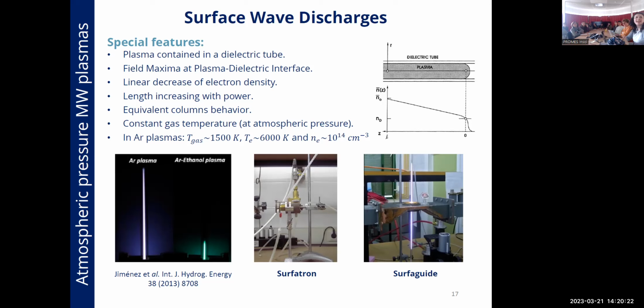Okay, what I was saying is that we are working with two kinds of microwave discharges. The first one, presented in this slide, is what we call surface wave discharges. These plasmas are created inside a quartz tube. Something very characteristic of this kind of plasma is that the electromagnetic field has its maximum at the walls, and it helps the propagation of the waves. Which are the characteristic plasma parameters of this kind of plasma? We are working with electron densities with these values, this energy for the electrons, and something very interesting is that all along the plasma column, we have more or less the same gas temperature. So the energy of the ions is quite constant along the whole plasma column.